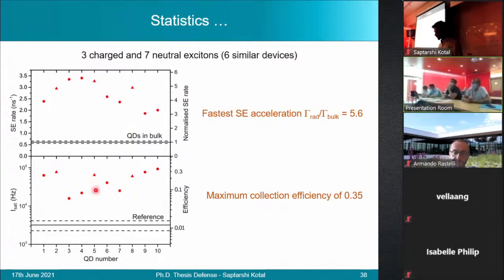Now, in these graphs, I summarize the results obtained across 10 excitonic lines taken from nanocavities of similar dimensions. The triangles correspond to charged excitons, and the disks correspond to neutral excitons. The fastest line I measured had a spontaneous emission rate of the order of 5.6, and the brightest line that I measured had a collection efficiency of the order of 0.35.